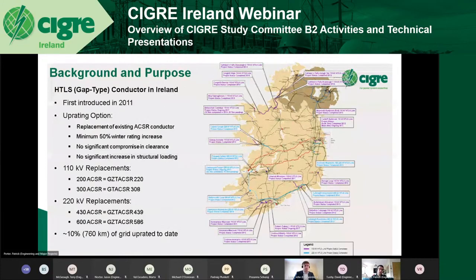So just a quick background on HTLS conductor, the gap type conductor. It was first introduced back in 2011 as a direct uprating option for your conventional ACSR conductors here in Ireland. The key function of an uprating conductor was to provide a minimum 50% winter rating increase. But also, very importantly, a key selling point is that you have no significant compromise in your clearances and or structure loading. So the benefit there to utilities is that you can utilize your existing assets as much as possible where feasible.